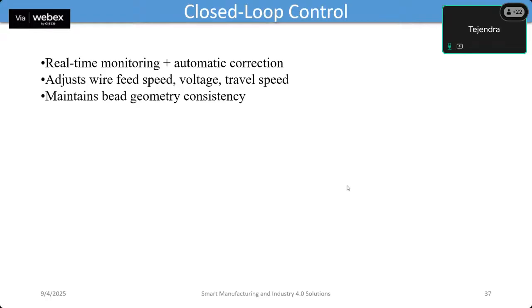Also, as we are using sensors for real time application, a closed loop feedback system is very much required. Closed loop control is the most important aspect of smart manufacturing. In simple words, the system is continuously monitored and automatically corrected in real time. With the help of the outcome that we are generating, we can easily alter the process parameters used in the process, through which any defect that arises can be eliminated. For example, if the bead height starts becoming too tall or too short, the system immediately adjusts the wire feed speed or the travel speed to bring it back to the desired level.